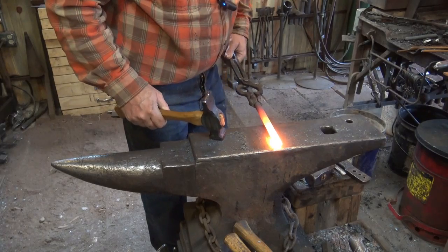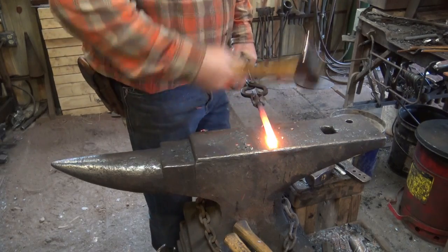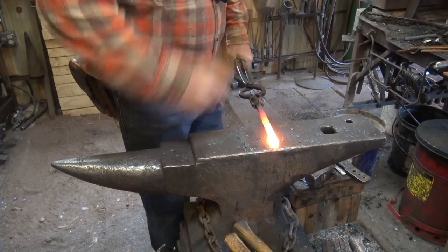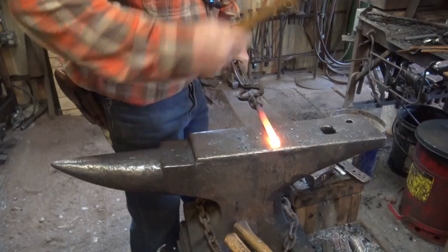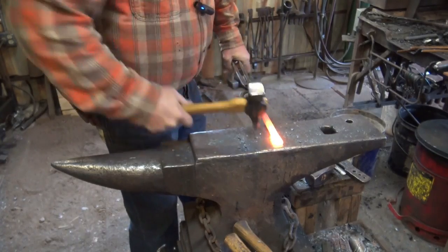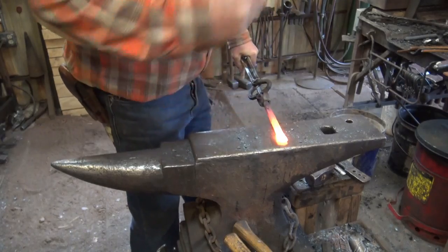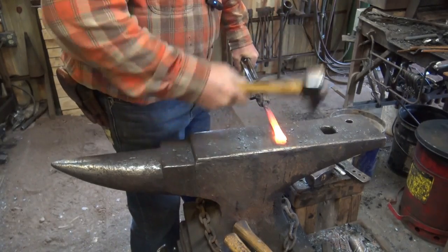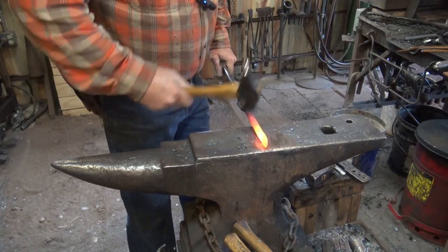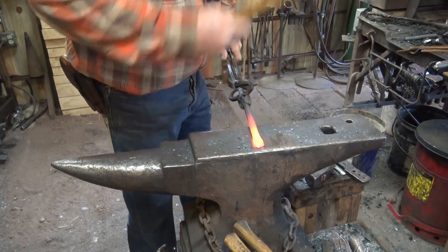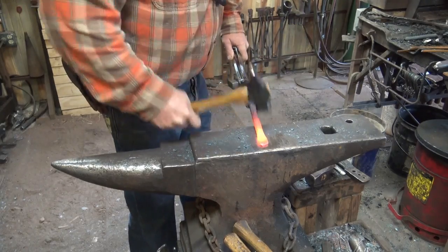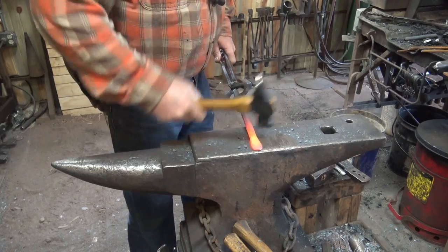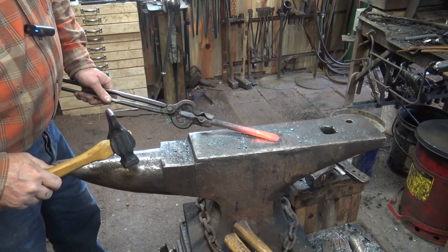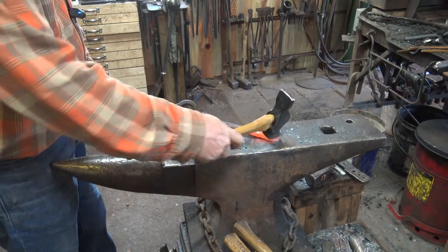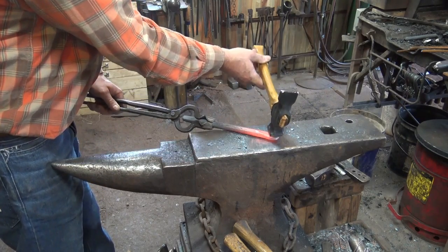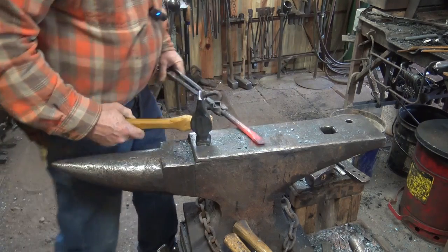So once you have your octagon, we can turn this into a chisel. It's just a matter of spreading this out. You might want to use your cross peen and work from both sides, but don't go too far with the cross peen. You may have trouble getting those marks back out. Now I'm lifting my tong end up to match the angle that I'm tipping my hammer. If you work flat, all you're doing is pushing this back and forth from one side to the other.